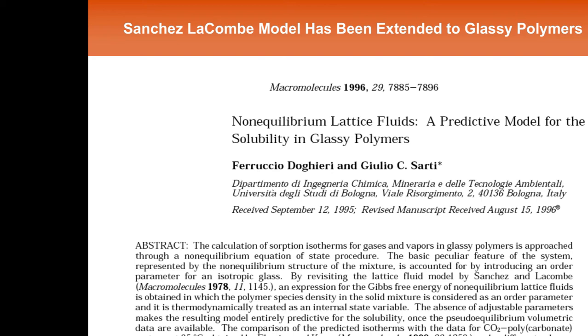You go up to a little higher partial pressure, or partial fugacity, of butane in the gas phase, and methane comes down some more. And at the highest partial pressure, 1.62 atmospheres or fugacity, look, what does the methane isotherm look like? Henry's law. So what does that mean?